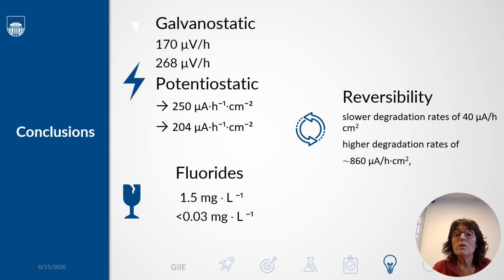Second, fluoride emission tells us a very clear story about chemical degradation. Only the Nafion 1110 assembly shows clear evidence of chemical attack of the polymer backbone. So the iridium-ruthenium oxide anode catalyst provides effective protection against oxidative chemical degradation of the membrane, even though this membrane is thinner. Third, the regeneration procedure with sulfuric acid is effective, but its durability depends strongly on the assembly.